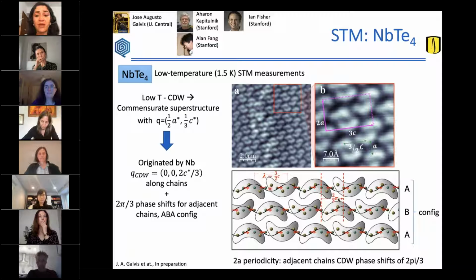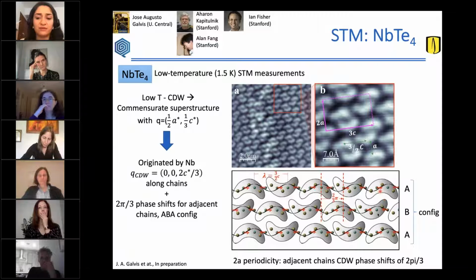So we are also able to observe the information regarding the vector of the charge density wave in this compound, and the different stacking of the charge density wave formed not by the tellurium trimerization in the surface, but by the niobium trimerization, which we are not able to directly observe. But given an asymmetric distribution of the charge density in the tellurium surface, and also due to our DFT calculations, we are able to deduce that the trimerization and the charge density wave formation occurs in the niobium atoms in this compound. And we have a stacking that is very characteristic, which gives the patterns that we see for these superstructures.